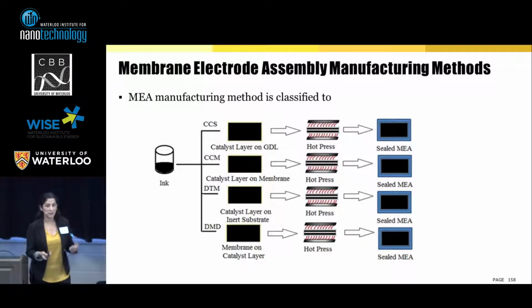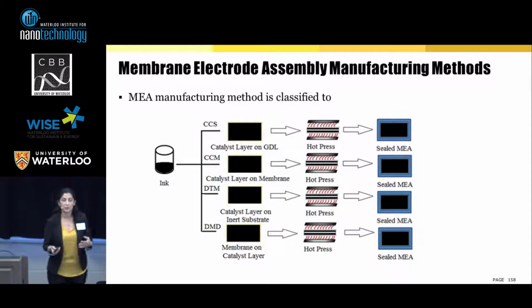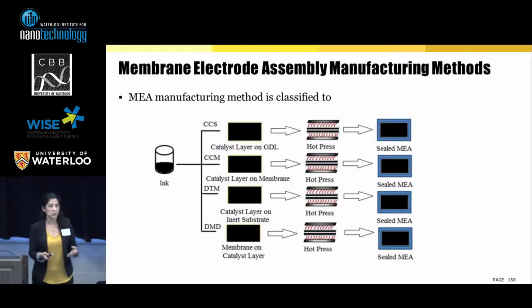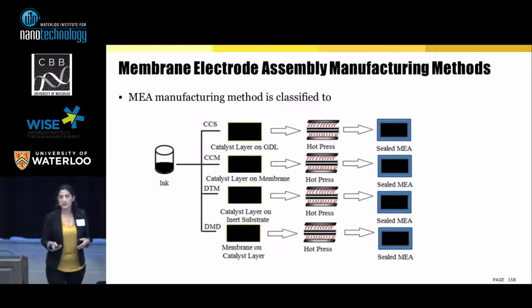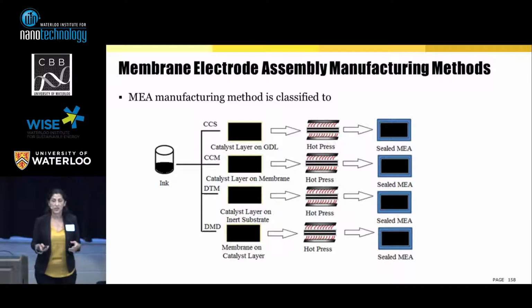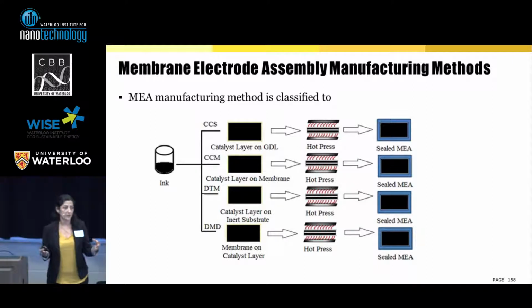So far, we have 3 main methods, and recently they added a 4th method for producing the membrane electrode assembly, classified based on where we put the catalyst. The first one is catalyst-coated substrate, where we directly deposit the catalyst on the substrate or gas diffusion layer. The second one is the catalyst-coated membrane, where we deposit the catalyst directly on the membrane. The other is the decal transfer method, where we have an inert substrate and we transfer the catalyst through the inert substrate to our electrolyte or membrane. And recently they announced a new method, DMD, or direct membrane deposition, that just works for a small size of MEA, because if we go to an industrial size or bigger size of MEA, we have a leaking problem. So for now, we are focusing on the 3 main methods.